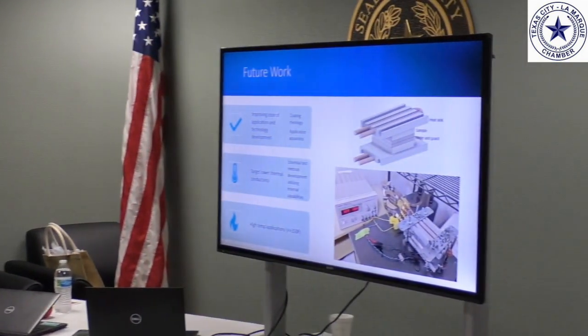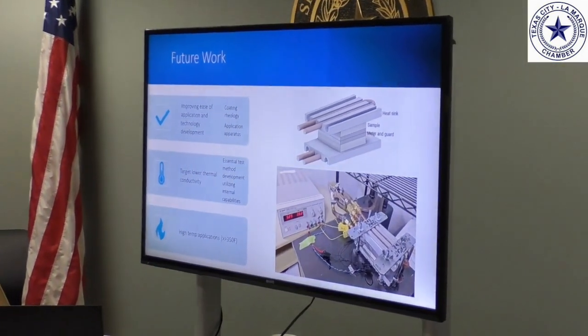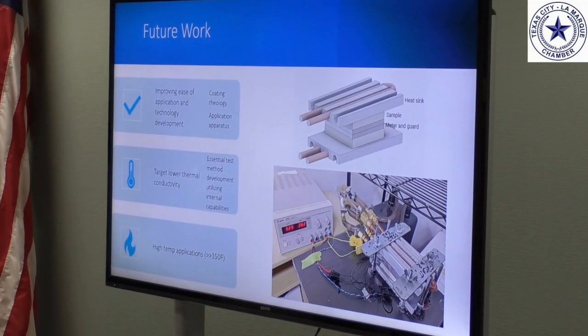Future work, we are looking to improve on this technology, even though we think it's very robust, and we're trying to improve the ease of application. We're also working on having a better flow leveling of the coating to give us a smoother surface, and looking at various application apparatus. We're also looking to have even lower thermal conductivity. Today we're at 0.06 on the base coat and 0.07, 0.08 on the top coat. We want to go even lower because some applications require us to have higher thermal efficiencies. And then we're looking at higher temperatures. Could we exceed 350 degrees F in the applications?